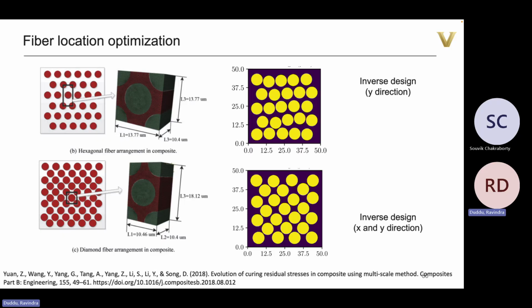And in fact, if you look at the literature, you do have these structures, right? This is the diamond fiber arrangement, which is what we were getting when you optimize both in X and Y. If you optimize only in the Y direction, then you get the hexagonal type pattern. So we were encouraged by this, but nobody will ever do something so complex and get this, which is already well known, right? So what was the point of it, you could ask. And so we don't know, because we started with curiosity. Sometimes that's the downside of doing something just based on curiosity and not based on outcome.